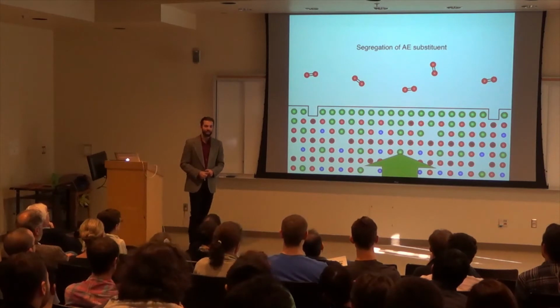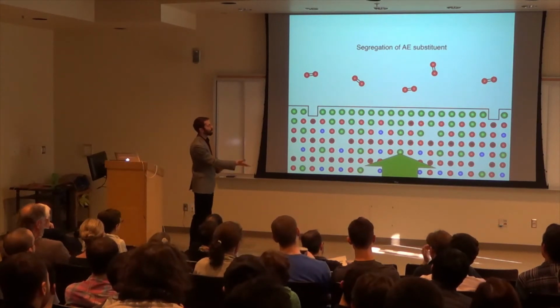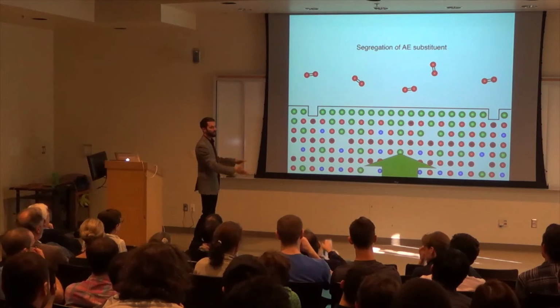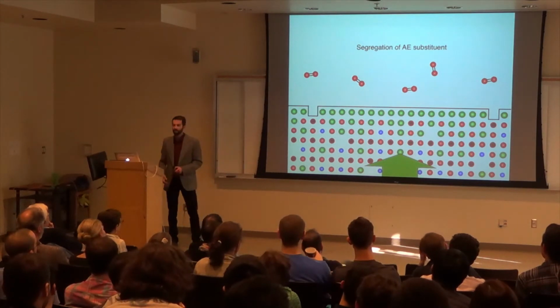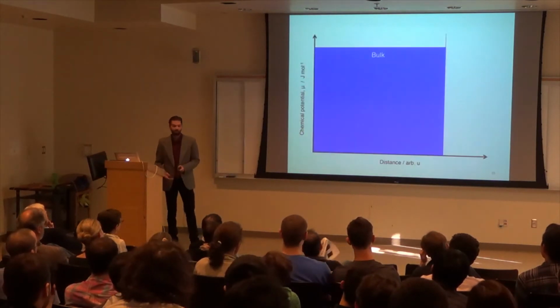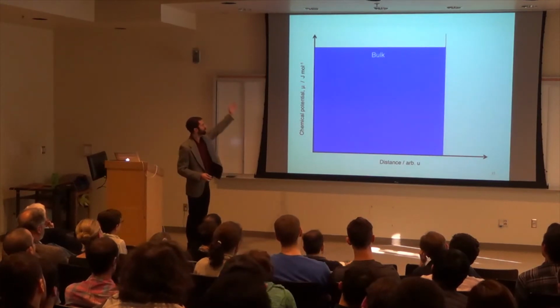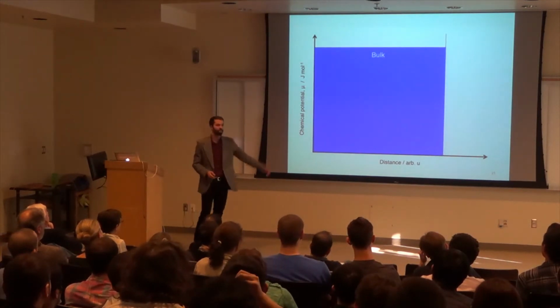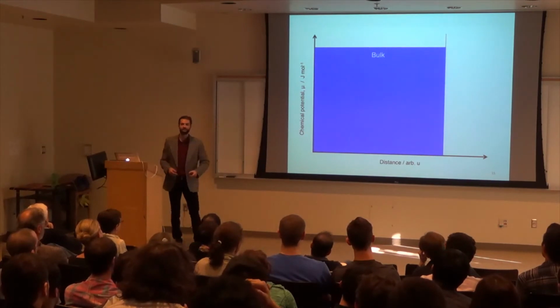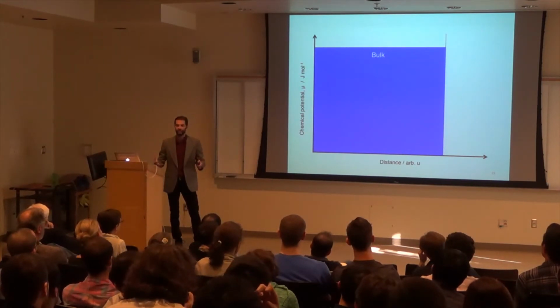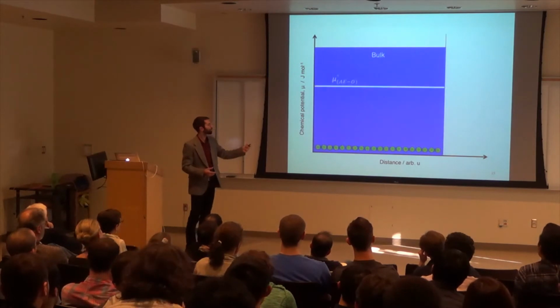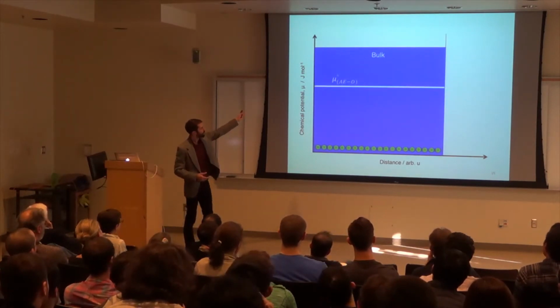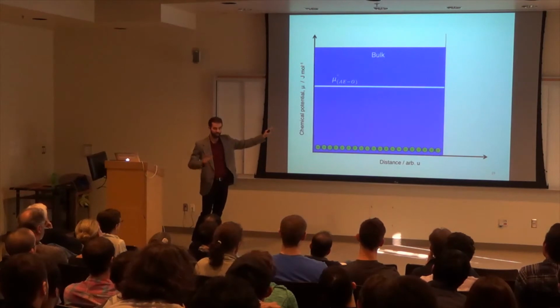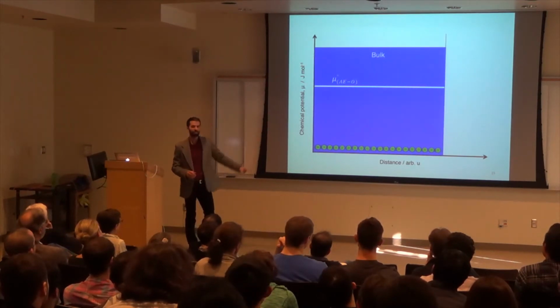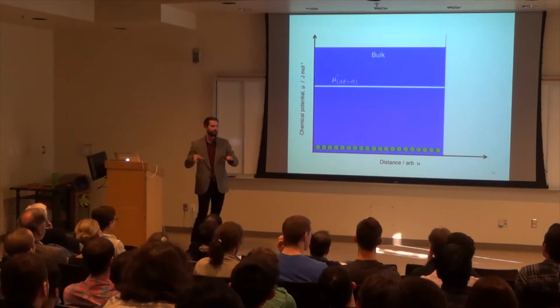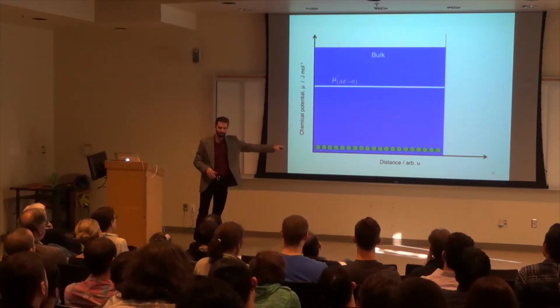We have this thing called segregation, where the cations can move from the bulk of the material, essentially this infinite reservoir, and come to the surface. Now let's see why that might happen. So here I have the chemical potential of some species on the y-axis as a function of distance on the x-axis. Now the chemical potential can be thought of as a driving force for anything to happen. Okay? In the bulk, this is the standard chemical potential for an alkaline earth, AE standing for alkaline earth. It's relatively flat, meaning there's no driving force for anything to really move around too much. And that's represented by this distribution on the bottom of the atoms.